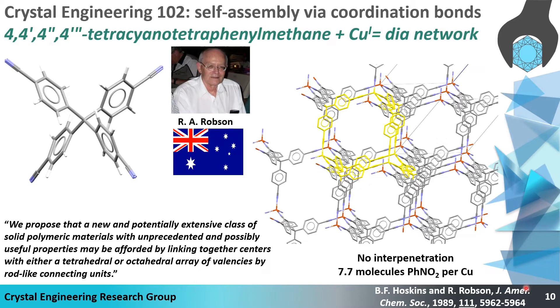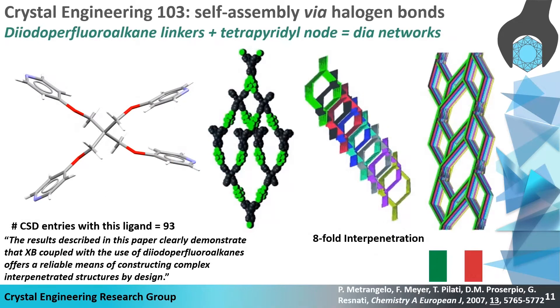In that case, large cavities were generated that included 7.7 molecules of nitrobenzene per atom of copper. Interestingly, this ligand has not been widely studied since — the Cambridge Structural Database only has two entries with it. It's fair to say this compound is the precursor of what we now call MOFs. Crystal Engineering 103 came later from the group of Resnati and Metrangolo in Milan, Italy, who reported self-assembly via halogen bonds to build DIA networks using a tetrakis pyridyl ligand and a dihalo linker.